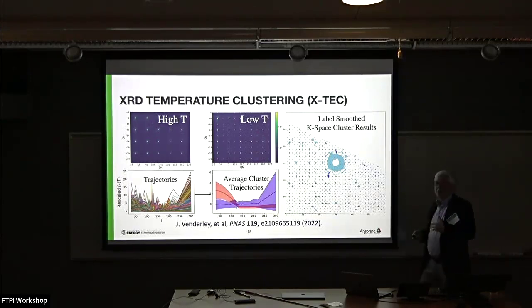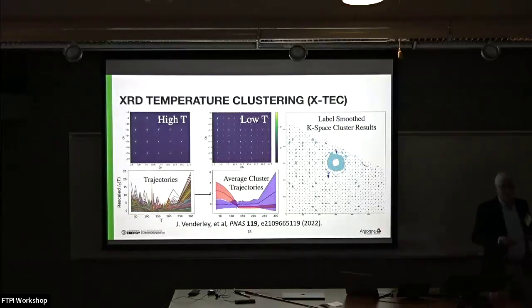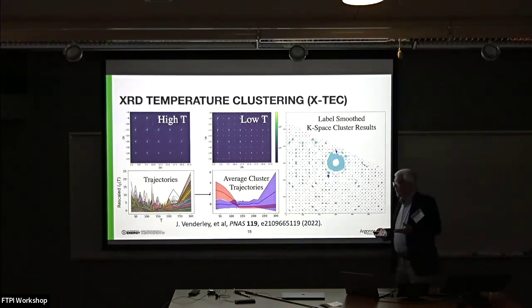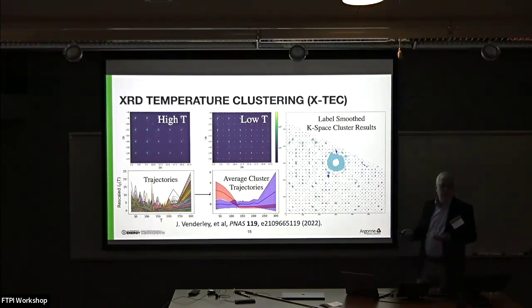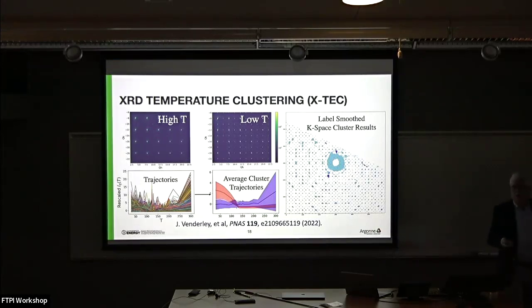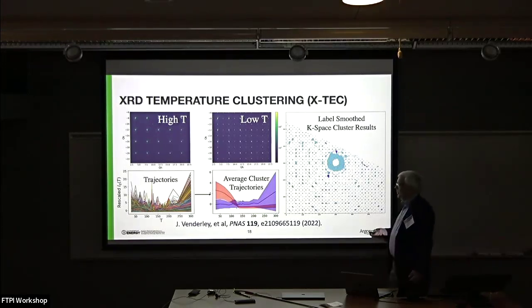Well, here we're producing a column map of reciprocal space, telling you where all the interesting temperature dependencies are. This is useful as a tool during the experiment, particularly if you can do it in real time. If we parallelize this, we can do it in something like 15 minutes, even though we're dealing with hundreds of gigabytes of raw data, certainly about 100 gigabytes of processed data. You can do it in about 15 minutes.